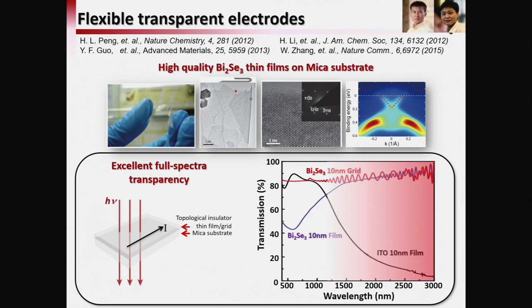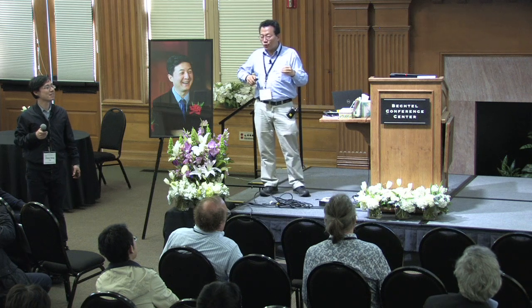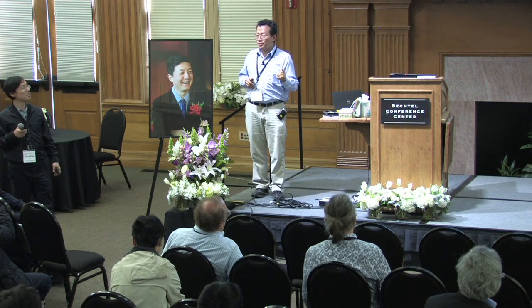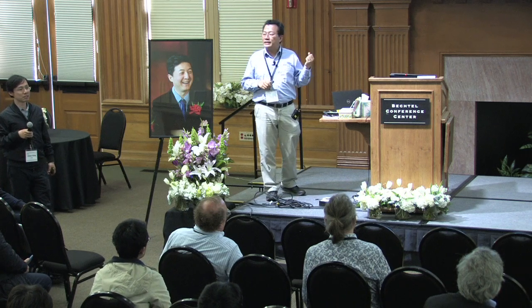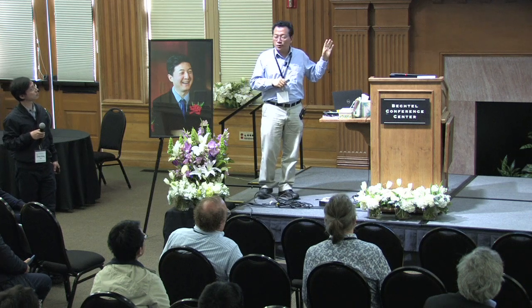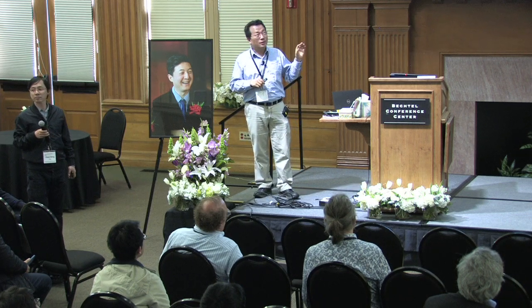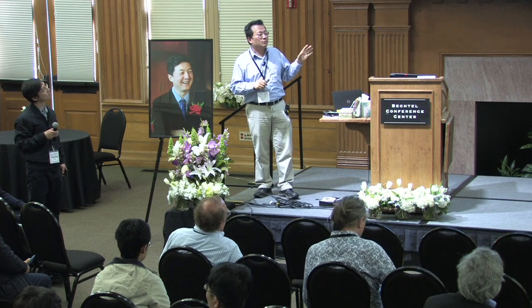If graphene is an ideal Dirac sheet, I don't remember, but transmission loss is 2% per layer or something. In this case, it's pretty thick, so with one layer of graphene there's a practical problem. One advantage of this system compared to graphene is that preparing a large sheet of single crystal graphene requires very high temperature, 800 to 1,000 degrees Celsius. That's not compatible with OLED. For this material, the growth temperature is 280 degrees. That's compatible, so it's good for a flexible transparent electrode.